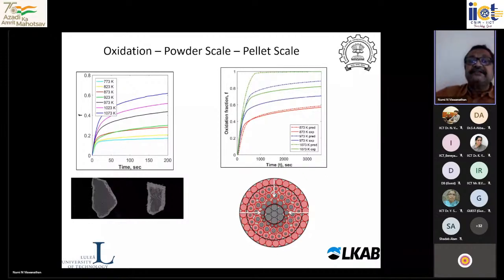The sintering characteristic of this Fe3O4 is different from the sintering characteristic of Fe2O3. Rather, Fe3O4 is easily sinterable. So it shrinks faster compared to the one which is outside. So what happens at plant level quality is that the inside is not yet oxidized, so it will shrink, and once it shrinks, it will come away from the bigger pellet. So if you take these pellets and shake them, you will hear a noise like a copra, dried coconut.